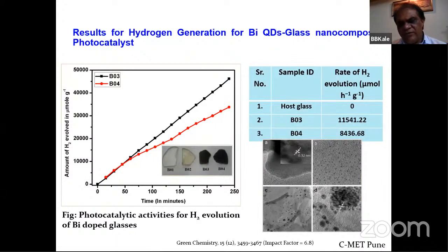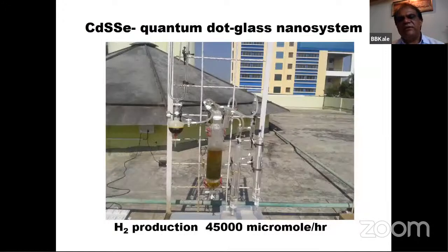So for the first time we have shown that the glass can also work as a photocatalyst, and it will be stable. The beauty of this photocatalyst is that it doesn't deactivate easily, because it's steady. Suppose you do a number of experiments and take the glass out, wash it with normal water, and use it again, you will get the same capacity. That is the advantage.